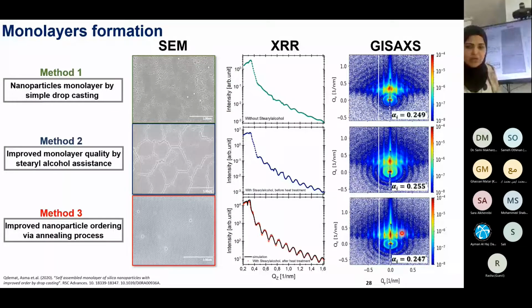along the QZ direction, which is due to the monolayer nature, and we also observe some diffuse rings which come due to the form factor of the single spherical nanoparticle. But what we can see as the difference is that the Bragg rods along QY in the monolayer of method 3 are more pronounced than in method 1 and method 2.